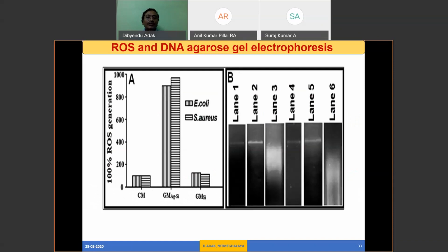Similarly, in the reactive oxygen species study, what we have seen is that the oxidizing agent or free radical, such as superoxide ion or hydroxyl with an unpaired electron, is much more unstable. It will react with your bacterial DNA and mitochondria to stabilize its unpaired electron. They will take part in oxidation, and during that oxidation, they will destroy the DNA and mitochondria. So we can see that the silver silica-based geopolymer mortar has much more reactive oxygen species than the control mortar and the geopolymer mortar with the silica.